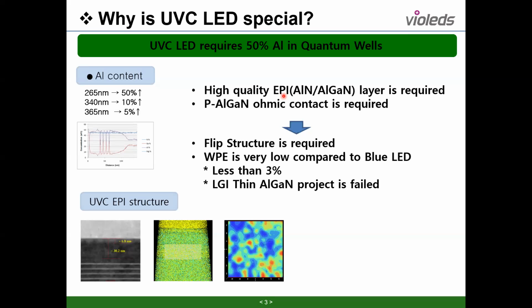Another hurdle is how to make the p ohmic contact layer. Because of this transparency problem, every UVC product LED has a flip chip structure. It means the light does not come from the top layer, it comes from the backside, the sapphire layer, so a flip structure is required. From all of these, the wall plug efficiency is very low, about 3%. That's one hurdle, that the efficiency is low. But as I said, we already have some experience in LEDs, and that will be overcome very well. And Seoul Viosys has developed UV LEDs for more than 20 years, and the second generation technology will help improve this UV technology also.